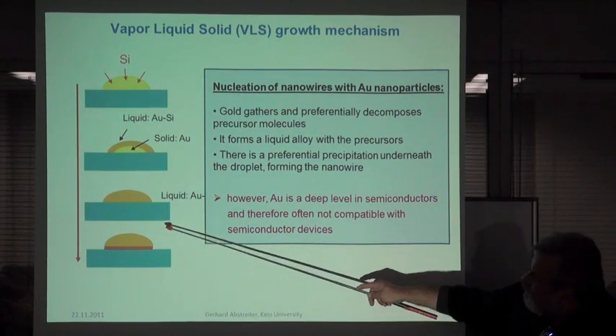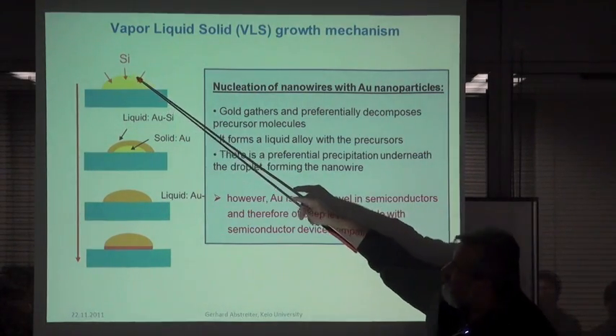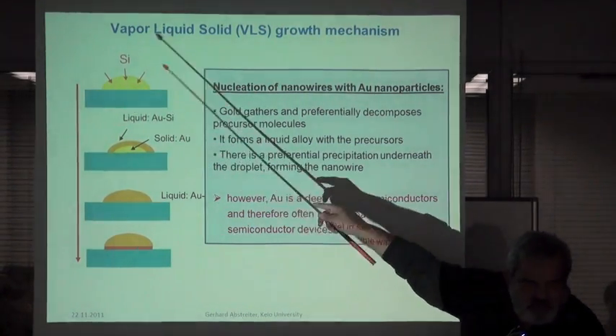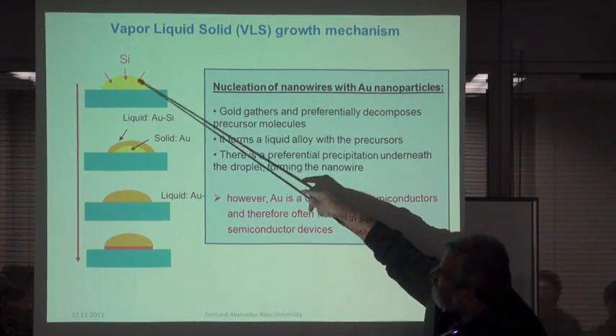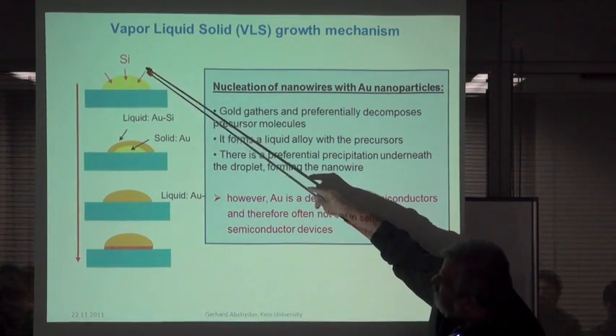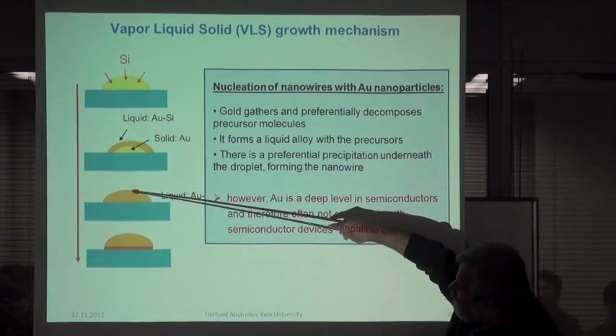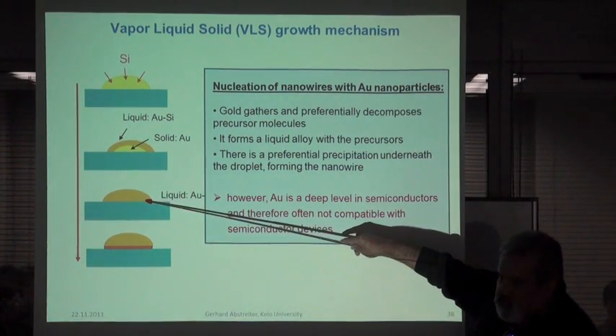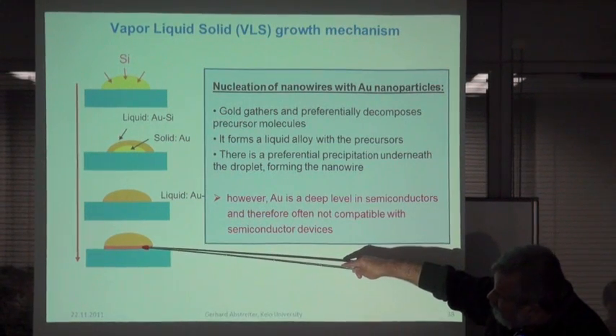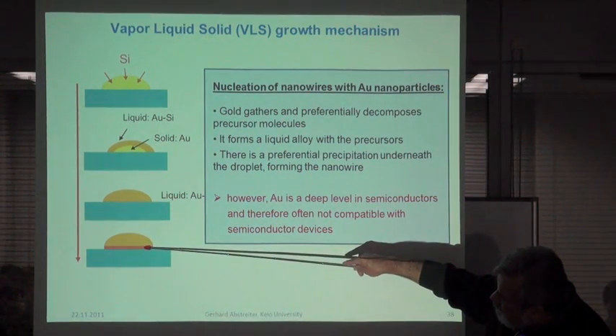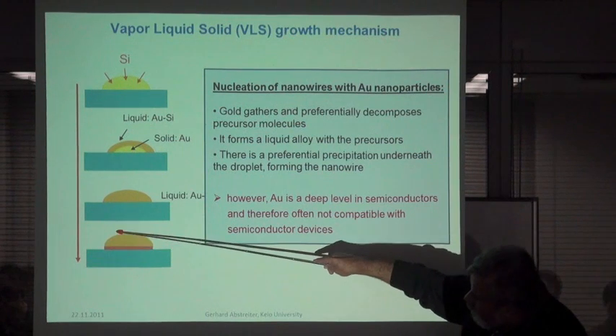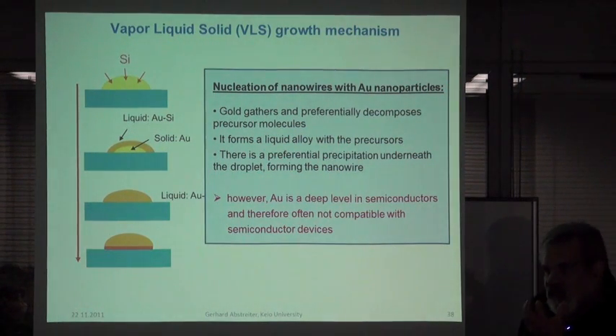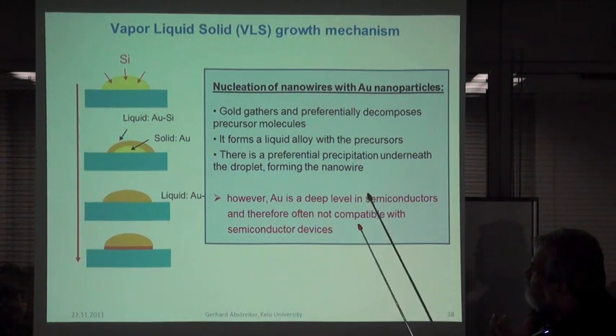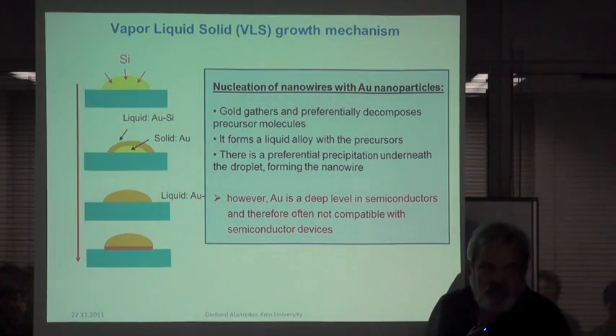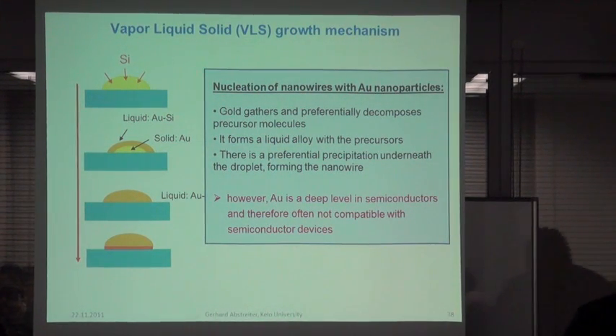So what people do normally is they have a droplet of gold, then you put in silicon in any form, can be also from more chemistry side, and then you get the saturation of this liquid at a certain temperature. And if you are super saturated, you start nucleating the silicon, and then the wire grows, and the droplet is just shifted up. So it acts as a catalyst. That's why one says gold is a catalyst for this growth. It's not incorporated apart from what under this temperature and conditions you incorporate as impurity.